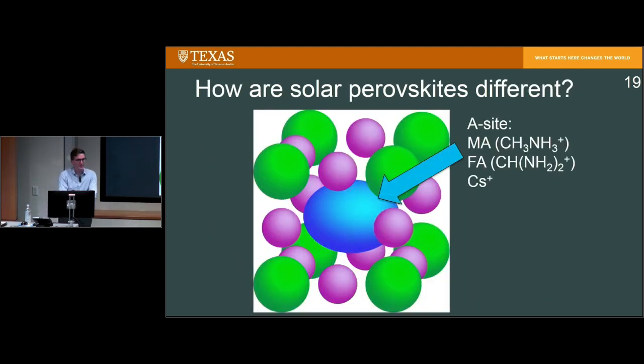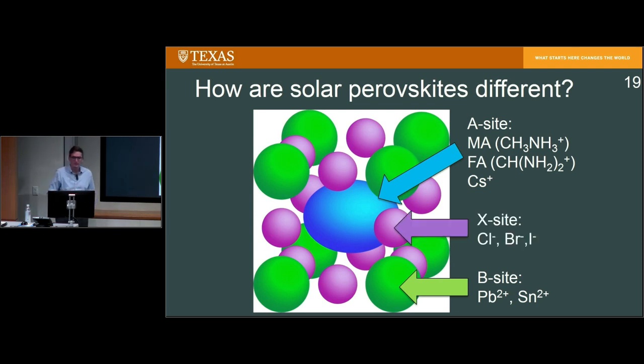And so our perovskites, instead of using calcium, have an A site that is usually an organic cation. That's why you might sometimes hear them referred to as hybrid organic-inorganic perovskites, because they have an organic component, and it is usually a carbocation that is put in the A site. That's usually because most inorganic cations are too small to fit in that A site, so you need something fairly large, like a multi-atom cation, to fill that space. The B site is usually lead, but sometimes tin. And the X site is not oxygen, but rather something in the halogen series: chlorine, bromine, or iodide.